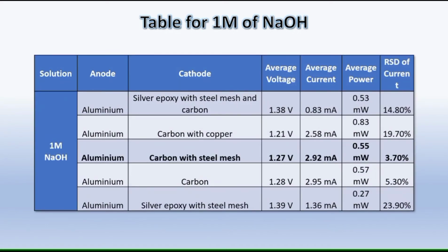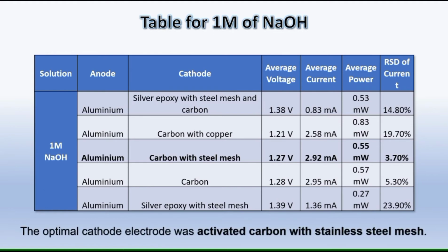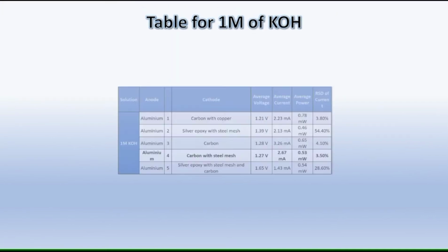We obtained these two tables via experimental data from a research paper. You can see the table containing different values of current, voltage and power. For the experiment, we have used 1 mole of NaOH solution as an electrolyte and different types of cathode and aluminum as an anode. After reading the research paper, we can conclude that if we use carbon with steel mesh as a cathode in 1 mole of NaOH solution as an electrolyte, we get maximum output. And the same for KOH solution. You can see the data on the screen.